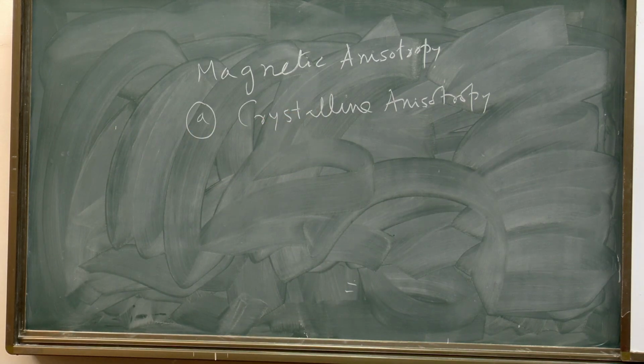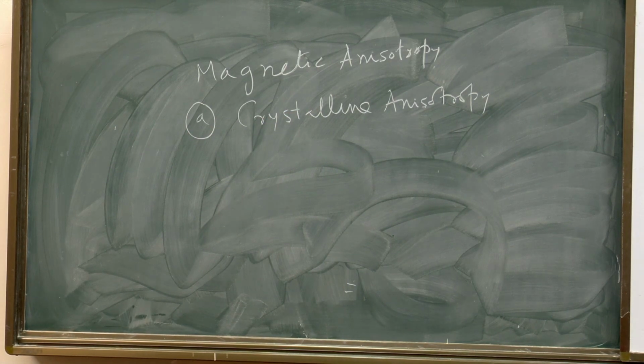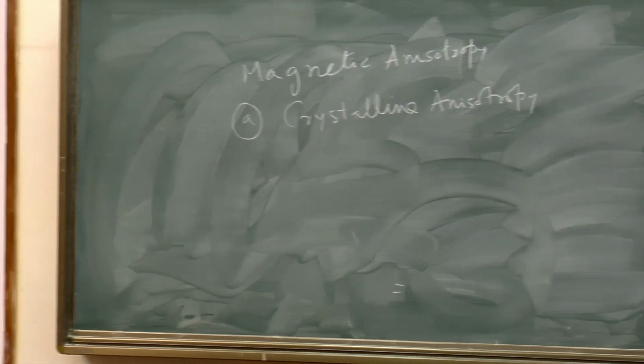Crystal by its own nature is anisotropic. The 100 direction is never going to be the same as the 111 direction, irrespective of the type of crystal. Let's take cubic. If you go along the 100 direction, you see atoms at a distance of a. If you go along the 111 direction, you see a distance of root 3 a. Band structure, everything is going to be direction dependent. Therefore magnetic properties are also going to be direction dependent. So there are certain directions in the crystal which are favorable. Magnetic anisotropy again arises because of a mixture of spin orbit coupling, crystal field and things like that.